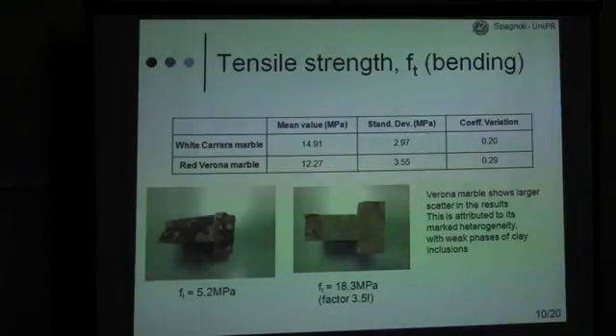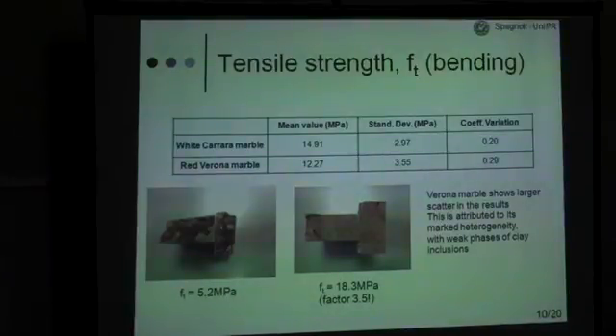And this can be attributed to the fact that there is heterogeneity in the material, and for instance, these are two results where you can see the fracture surface. On the left is what corresponds to a much lower tensile strength in comparison to the one on the right. So I'm picking here two extreme cases, and the lower bound is related to some weak phases in the material, which is due to some clay inclusions in the texture.